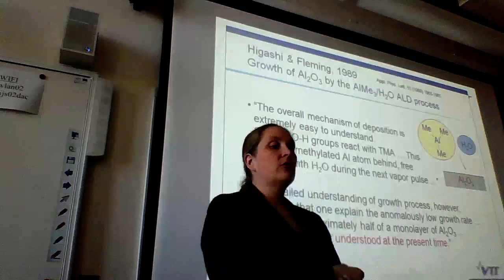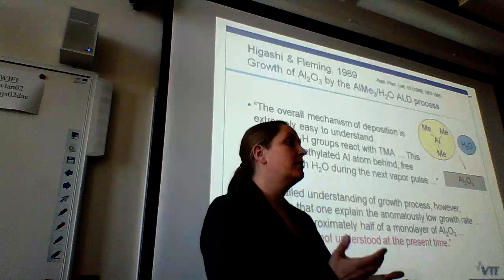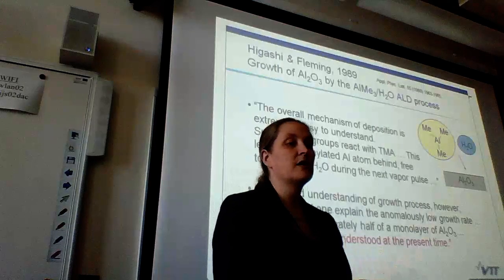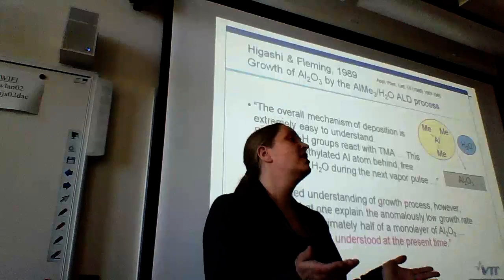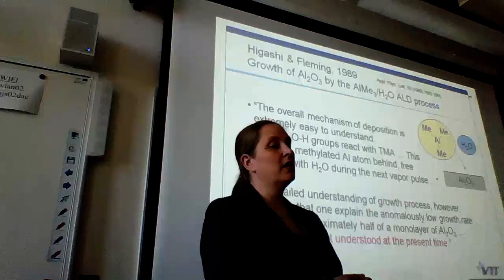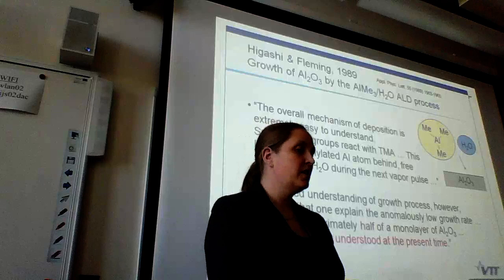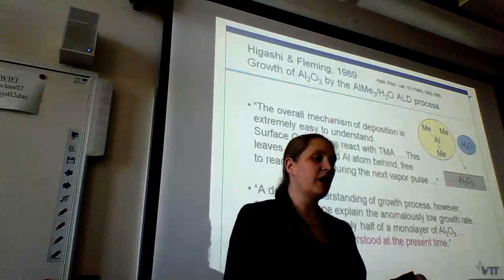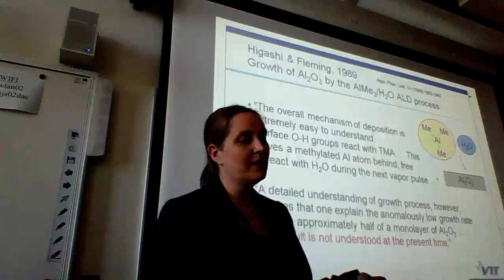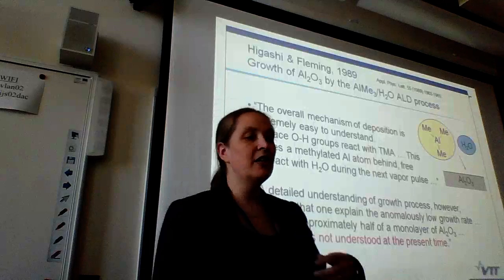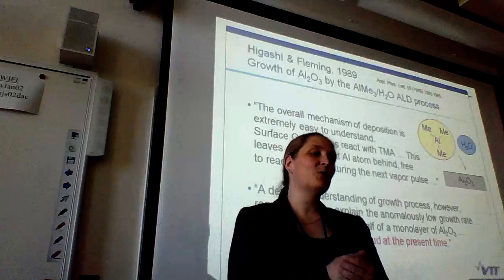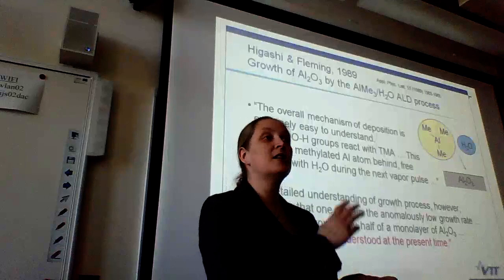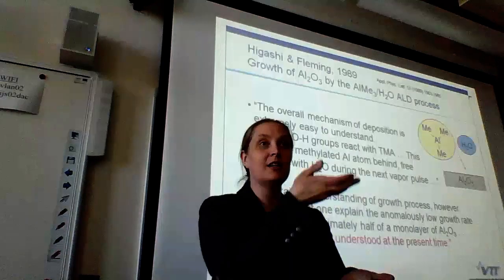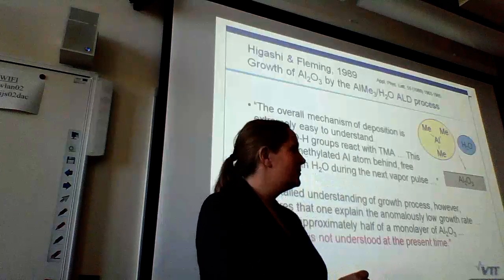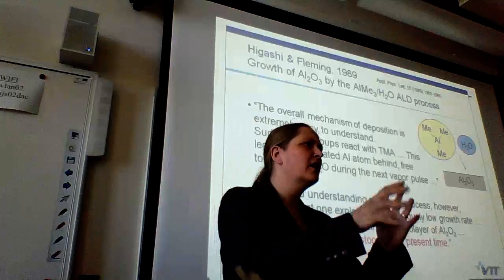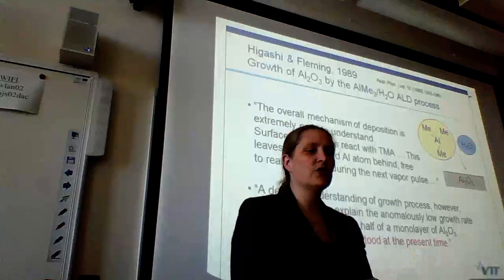So they were able to deposit aluminum oxide. We know that it's a really easy process. And the authors, Higashi and Fleming, said the overall mechanism of deposition is extremely easy to understand. Surface OH groups react with TMA. This leaves a methylated aluminum atom behind, free to react with water during the next vapor pulse. We saw this already today, right, in the Cambridge Nanotech video and other schemes.